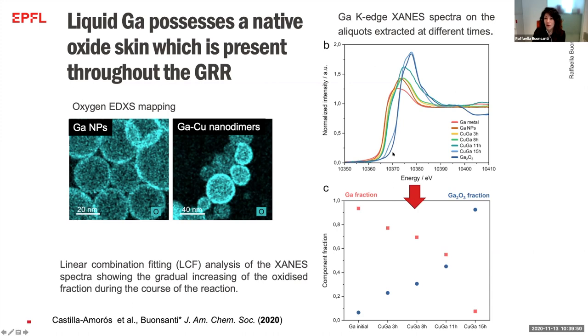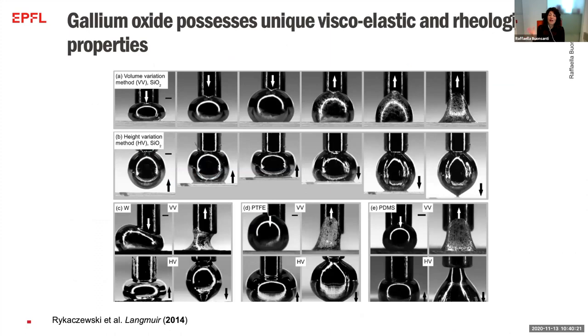And what we learn with this measurement is that actually the oxide is present. So this is the oxide, and our sample is always in between the gallium metal and the oxide, no matter at which stage of the reaction, which basically indicates that the oxide is present throughout the reaction. And the reason why the oxide fraction is increasing over time is because the gallium is eventually becoming smaller. And this is basically, what about the shape?